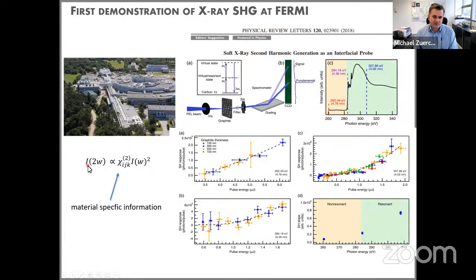Well, if we look back at the math, we measure an intensity at twice the frequency, say 2 omega, of our impinging electric field, and that's proportional to the square of the incoming intensity, and it is proportional to this chi2 tensor. So that's the dielectric second order susceptibility, and that's, like I said, a rank 3 tensor. So this is actually what we want to know. These tensor elements contain information about the dielectric environment, say, of a certain atom at the surface. And then, of course, from this we can draw a conclusion like, what does it mean if a molecule approaches and there's a charge transfer happening? That is when these properties will change, suppose we can do a dynamic measurement.